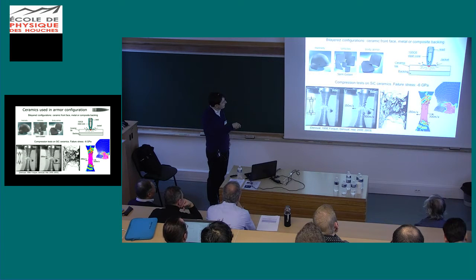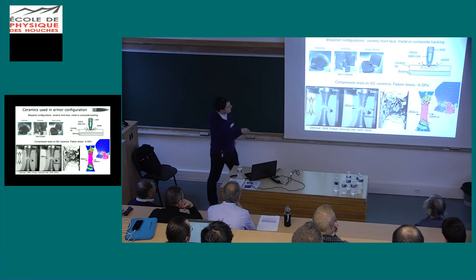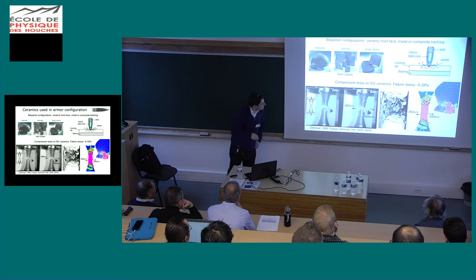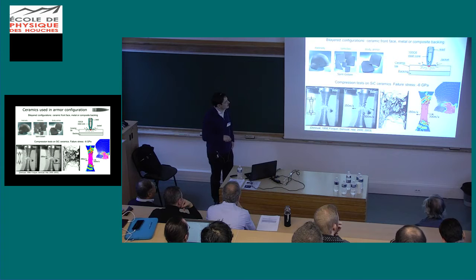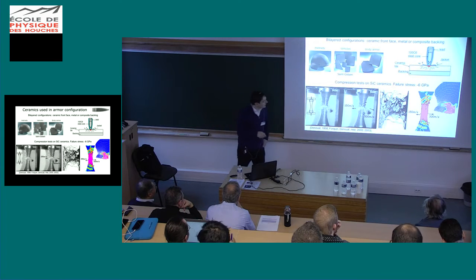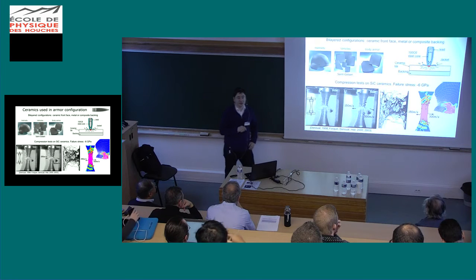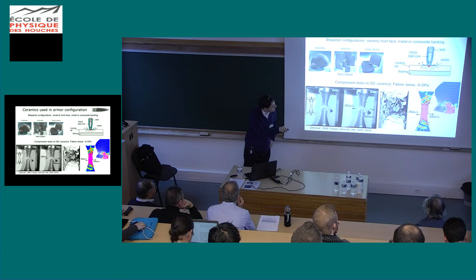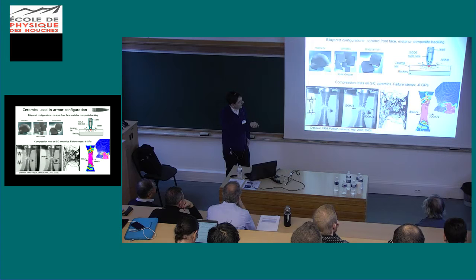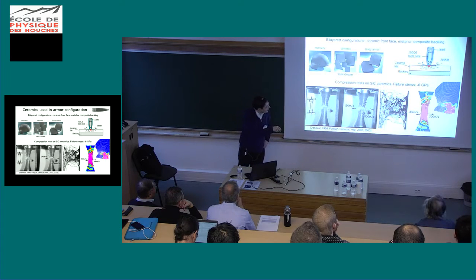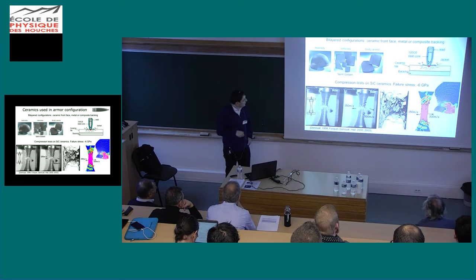And due to a release wave that propagates from the ligament to the entire volume, we generate an intense fragmentation. And you can see the amount of defects, the amount of cracks that were triggered and were propagating in the sample. So of course, this damage is not a compression damage; it is a tensile damage. Because as you can see in this numerical simulation, when the failure starts, immediately it started here. So the fragmentation occurred due to a release wave, and in fact the matter was completely projected in debris at a speed of about 150 meters per second.